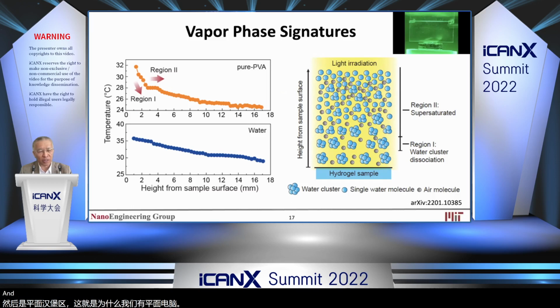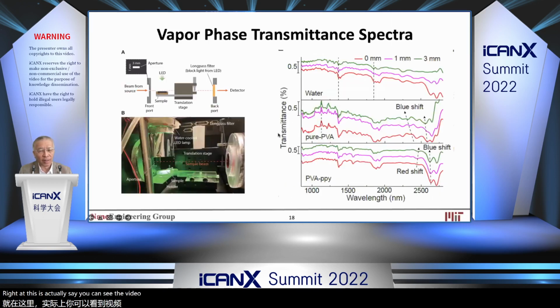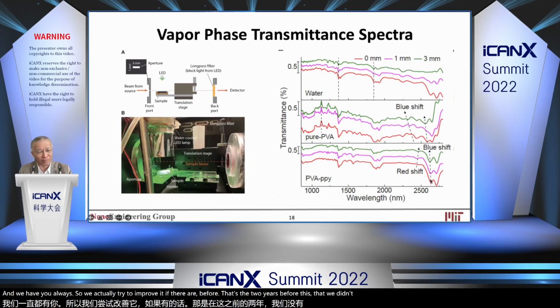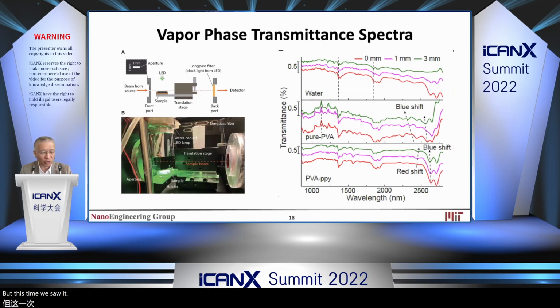And this was still not enough. I say, can we see the signature of cluster, right? And this actually say, you can see the video. So we measure the vapor transmission spectrum above the water surface, and we have NIR waves. So we actually tried the infrared FTIR before. That's 2 years before this. We didn't see it because we don't know what to look at. But this time we saw it. We use NIR waves.